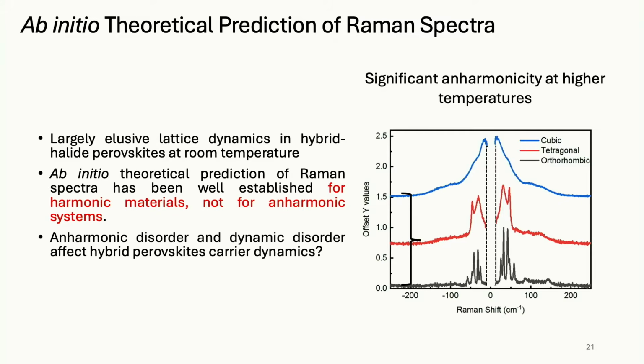So I think many of you are familiar with Raman spectroscopy. Raman is a great non-destructive way to probe the properties of materials. So you expect to see the vibrational modes that are Raman active. This is for a three-dimensional hybrid perovskite, but I would make the same point about the 2D ones. If you look at low temperature, you see a series of peaks. You would say, good, no problem, a Raman spectrum. But now look, as you go up toward room temperature, you get a very broad, weird double peak.